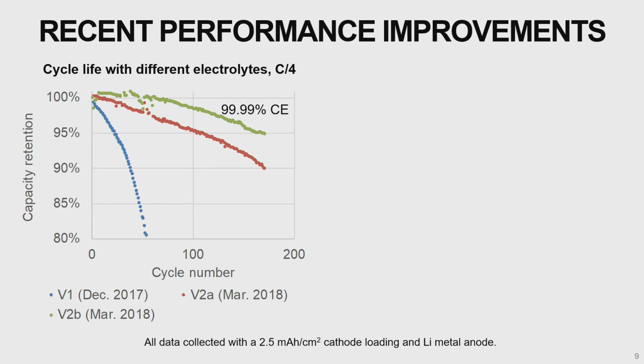So this is just one example of electrolyte improvements. Compared to what we had at the end of last year and what we did in March of this year, you can see for one particular type of cycling performance, we're getting substantially improved cycle life just with a new electrolyte system and no other tweaks to the chemistry. So substantially improved just in a few months, and this is really not fully tapped out. We anticipate further improvements as we continue tuning the electrolyte chemistry.